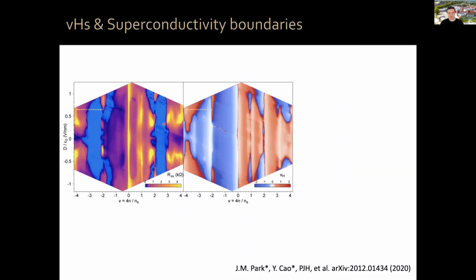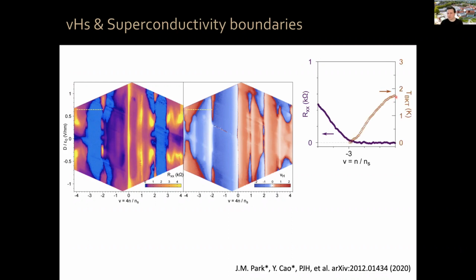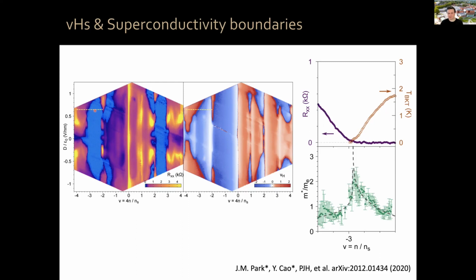If you measure resistivity along this yellow line, which is actually a little bit shorter than this line and doesn't quite reach this region, but is roughly at this electric field, you measure zero resistance here when there is superconductivity. Then you cross the boundary, and the resistance increases, of course, out of the superconducting state. Now you measure TBKT, the Berezinskii-Kosterlitz-Thouless transition, or if you want critical temperature, it's finite there, and it ends right when the system stops being superconducting. Now, we can measure the effective mass by measuring the temperature dependence of the Shubnikov-de Haas oscillations across this line too. And we can see that the effective mass diverges at that point. That point corresponds in our normalized Hall density to the Van Hove singularity.